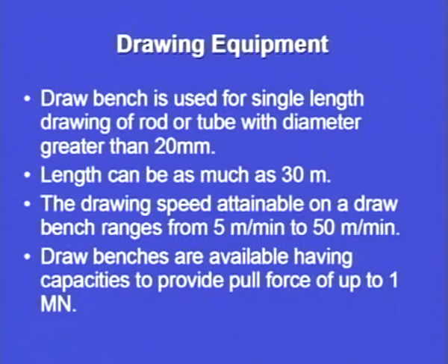Now a draw bench is used for single length drawing of rod or tube with a diameter greater than 20 millimeter, so there is a limitation on the diameter. If the diameter is greater than 20 millimeter, we can use a draw bench, and it is a single length drawing process. The length can be as long as 30 meters. So the length of 30 meters and the diameter of 20 millimeter are two important design aspects when we use a draw bench as a pulling mechanism for reducing the cross section of a wire or a tube.